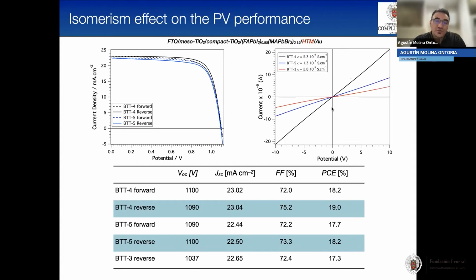So we have also measured the conductivity of these molecules, and as you can see here, the highest conductivity was obtained for BTT4, so it is in good accordance with the results from the IV curves. This is followed by BTT5, and the conductivity of BTT4 is 20 times higher than that of BTT3.